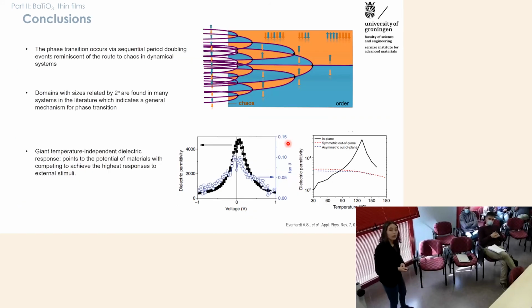So in conclusion, we have shown that the transition between these phases of barium titanate occurs through sequential period doubling events, which is quite a general mechanism and is quite known in dynamical systems as a route between order and chaos states. And if we look at the literature and we look at more of these ferroelectric materials, but also other kinds of materials, we find that domains with sizes which are related by this 2 to the power of n rule are quite common. And this might indicate that it's a general mechanism, not only for this specific system.